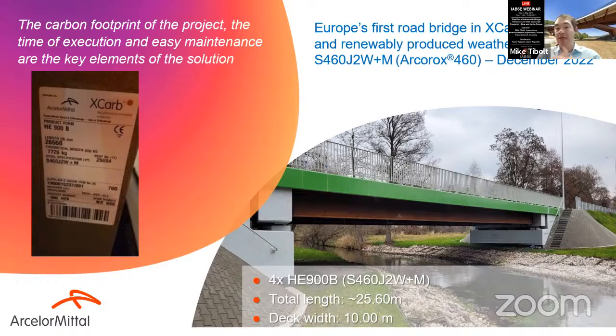And by combining it then with the X-Carb brand, of course, we can further reduce the CO2 footprint of the solution. And this was the driver to go for this solution. The bridge has been realized 4 weeks earlier than foreseen in the planning, because the construction was quite easy. And by using high-strength steel in combination with weathering steel, we could also have a lighter solution, because for weathering steel, as you know, you might apply a thickness allowance to consider the corrosion losses over the lifetime of the bridge.